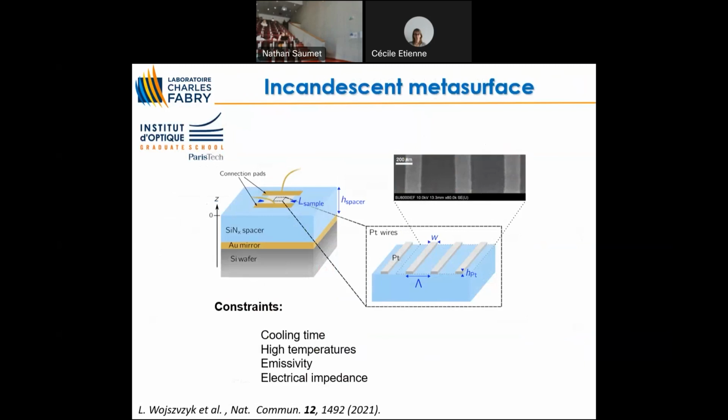So heat transfer is pretty fast at nanoscale. Now, the problem is 25 nanometers is not a lot of metal, and we want to absorb everything to be able to emit everything. Remember Kirchhoff. So to enhance the absorption, we use a mirror here, and we design this spacer in such a way that an incident plane wave will be reflected and will produce an interference that has a maximum, an anti-node, right here where we place the grid. We can optimize these things in order to have 100% absorption.